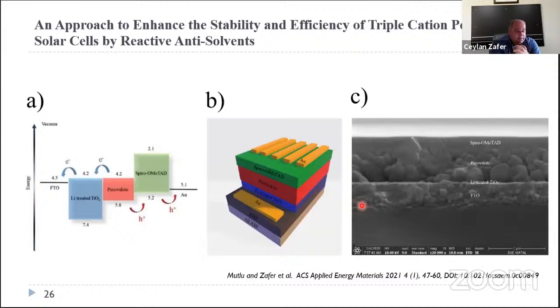In my talk, the new information comes with a new approach to enhance the device performance by playing with the solvents. In the literature, the conventional method is just replacing the solvents with ones of different polarities. But in our studies, we use reactive solvents that react in situ with the perovskite material and change the morphology. And one of them is chlorobenzene, replaced by different solvents like benzyl bromide or benzyl iodide. Here you see a normal energy alignment of the perovskite device with the two interfaces, the lithium treated titanium oxide and the spiro-OMeTAD interface. For this, we play with the perovskite itself, the crystal structure, and these two interfaces.